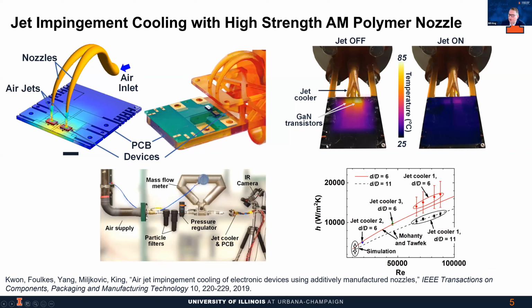You can see in the upper right infrared images of the GaN devices and the jet cooler, when the jet is on or off. So obviously we're cooling something. In fact, we get convection coefficients up to about 15,000 watts per meter squared Kelvin, in line with expectations.